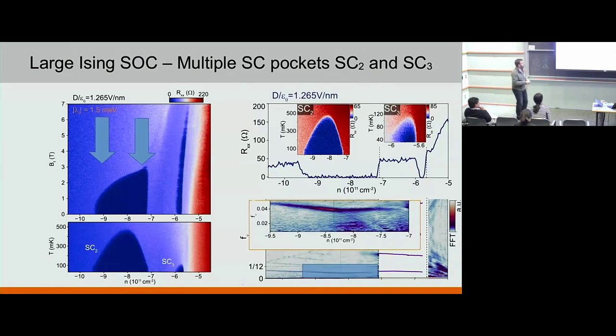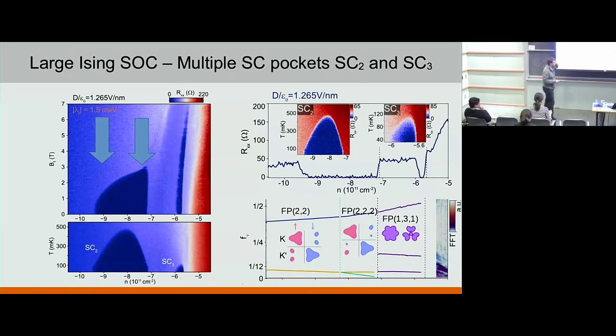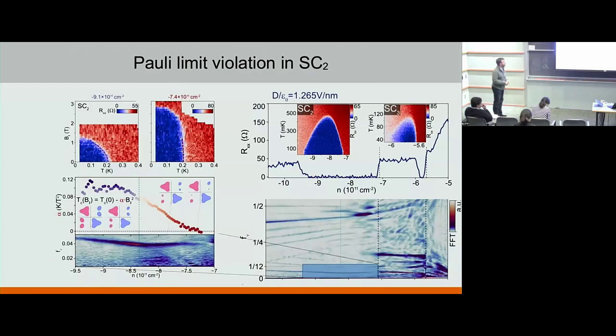And I'm running a little bit out of time, so I'm just going to show you the solution. The solution was that in contrast to this 2-2 phase, sorry about this, here we now have a 2-2-2 phase where these small pockets are starting. So one of these small pockets starts to shrink, and it shrinks down to almost 0 when you hit this phase boundary. And funnily enough, this is where you have this strong deviation from the Pauli limit relationship, this crookedness of the phase diagram.